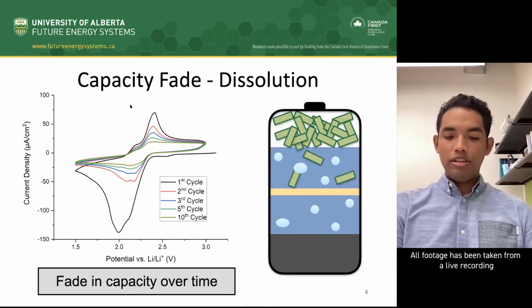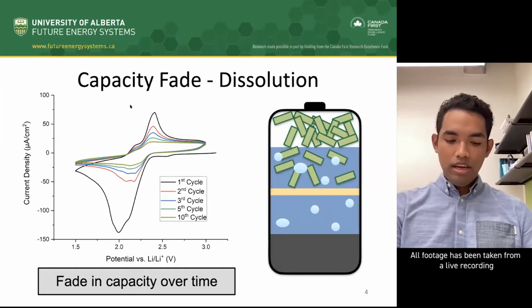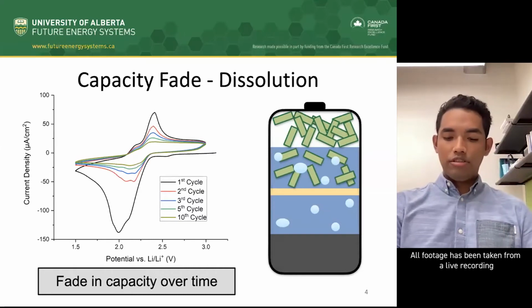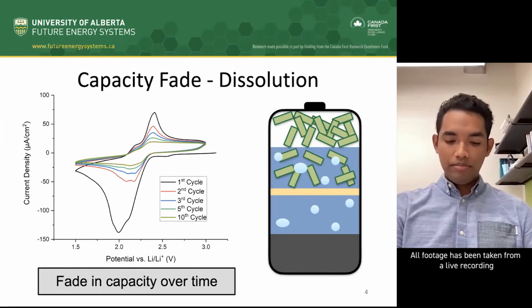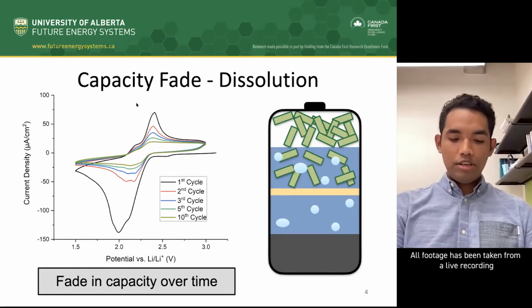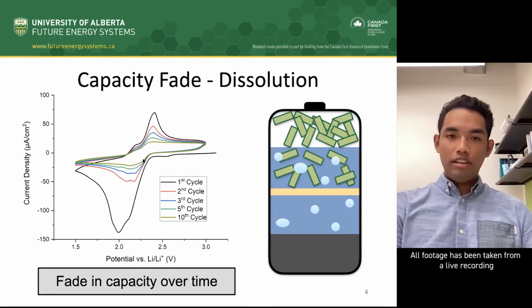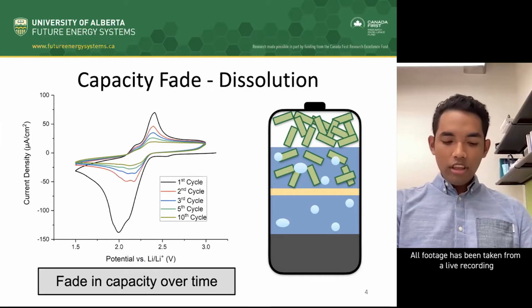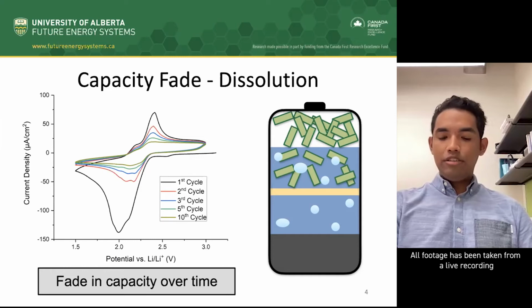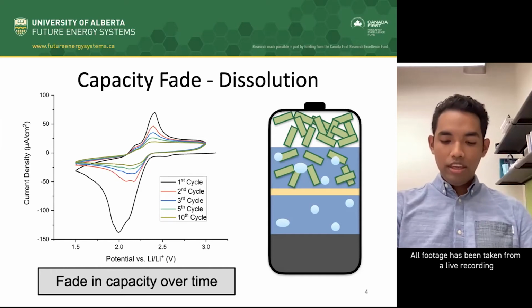In this little animation, we can see that the organic molecules forming the cathode are lost to the electrolyte, making them unable to participate in the storage of lithium during battery cycling. This concept was demonstrated by our experimental data, where we see a decrease in the current density, which indicates a decrease in redox events with each cycle, which can be attributed to the dissolution of active material. Future work will involve quantifying the rate and magnitude of capacity fade.